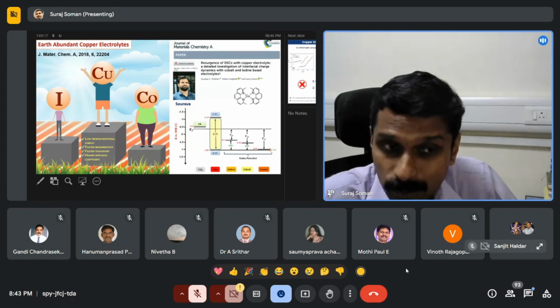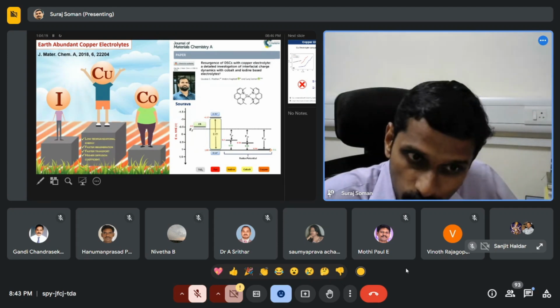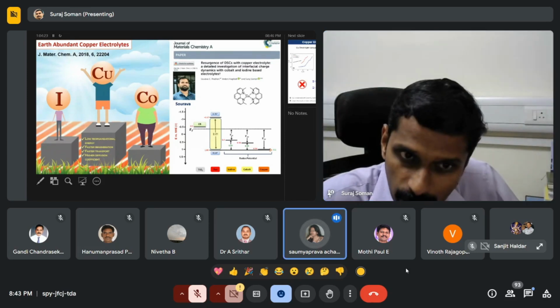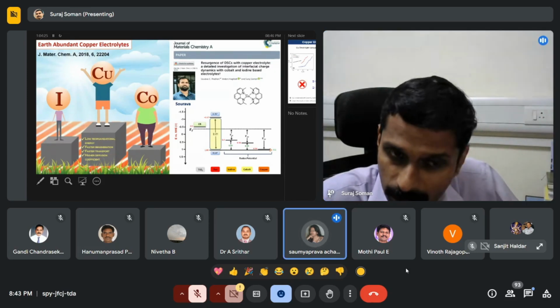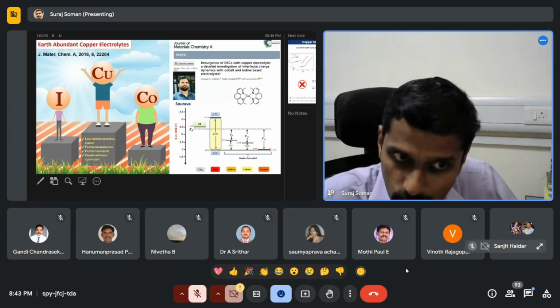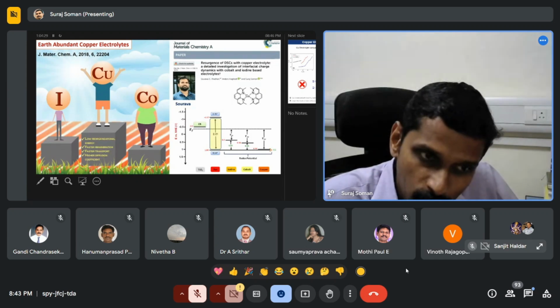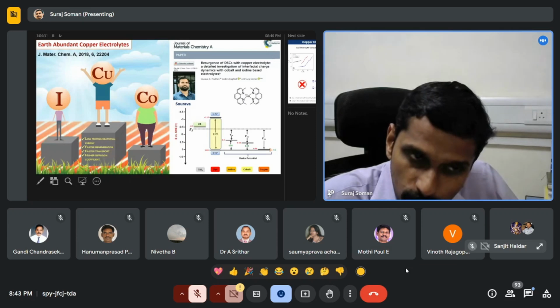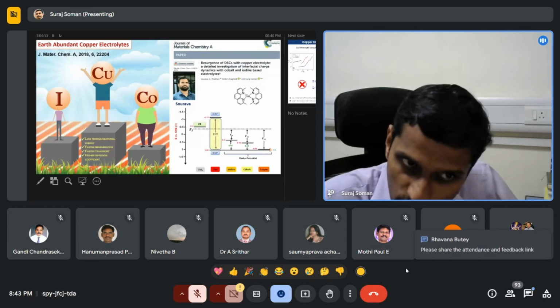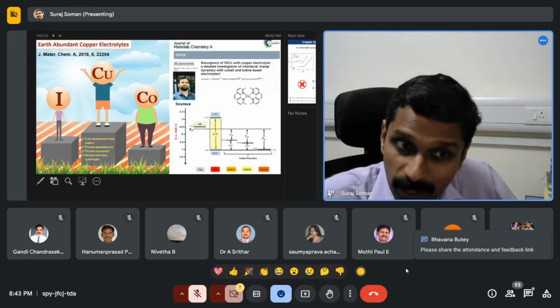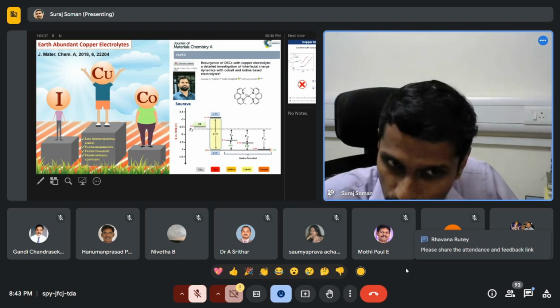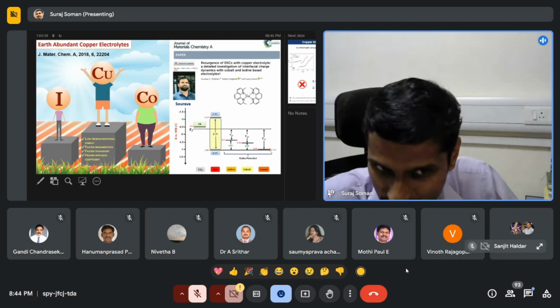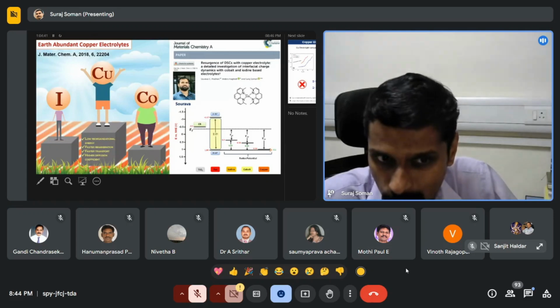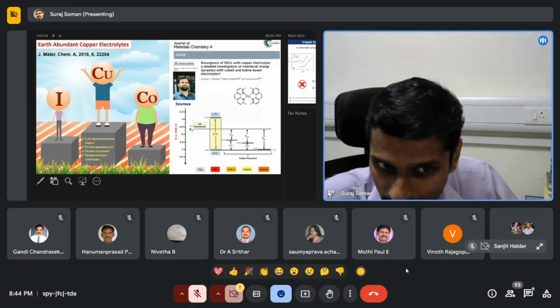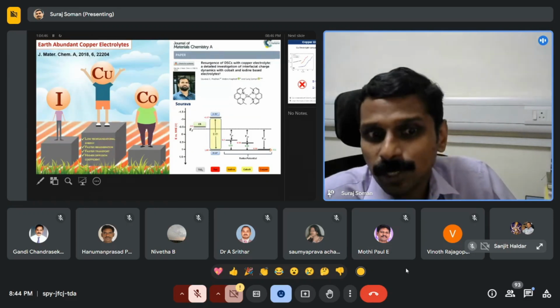So now come back to the initial point, whatever I told you. What is the voltage? The voltage is the Fermi level and the redox potential. So previously you have seen that by using a bilayer device, you push the conduction band to a more negative potential, you can gain more voltage. Here what is done, you changed the molecular system of the electrolyte from iodine to cobalt to copper. Thereby you can actually push the voltage.